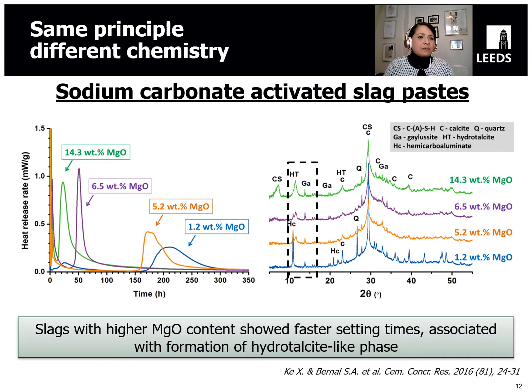So when I relocated to the UK later in my career, I realized that a lot of the comments I was getting during my presentations about alkali-activated cements were regarding the potential global warming effects of the activator, the safety concerns of using highly alkaline activators. So I started working on near neutral salt activated slag cement. I still work actively in that area. And one of the most promising ones was sodium carbonate.